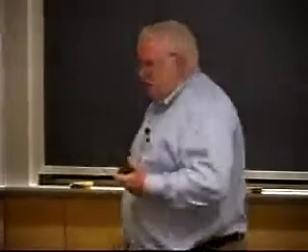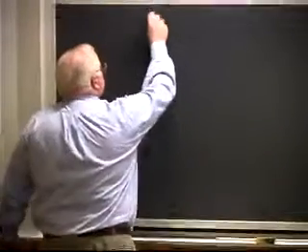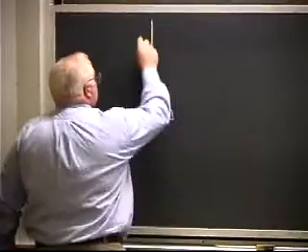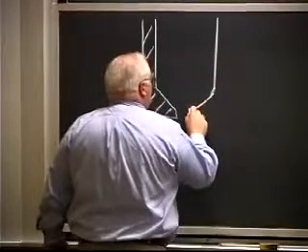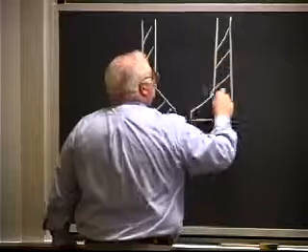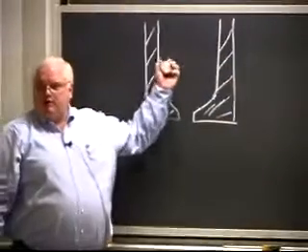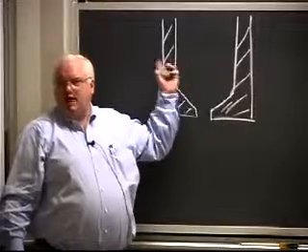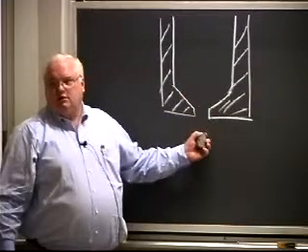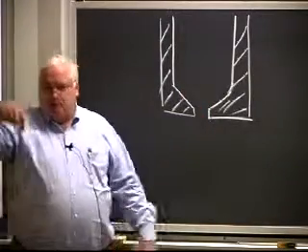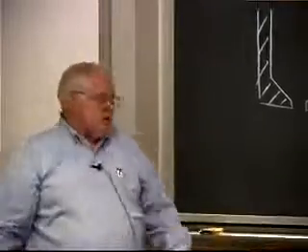But in the last 10 to 15 years, for cutting ordinary thickness steels, and that means up to about 1 or 2 inches, plasma cutting has displaced it for primarily environmental and productivity reasons. Essentially, plasma cutting is an arc burner instead of a flame. It's an arc jet burner. And remember, a jet burner was something where I mixed the oxygen and the fuel and combusted it inside the chamber at constant volume. So all the p dV work of the heating of the gas caused it to shoot out at very high velocity. And we talked about using oxyacetylene jet burners to drill through rock and things like that.